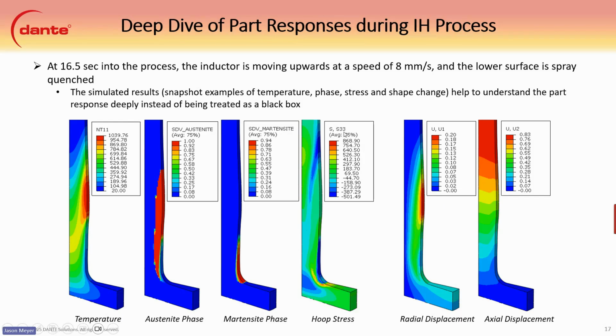But right now we do see in the S33, the hoop stress region here, a line of tensile stresses being formed under the case here. And again, just to drive it home, the stress balance here is really the most important thing. Only this region is being transformed into austenite, and then this region is being transformed into martensite. So it really only has this region to have the stress balance. And so it has this compression here. It needs to have some sort of tension in order to balance it out, and has this volume to do so. And that drives home and shows the phenomenon of the volume expansion from the martensite and its effect on the underlying material.